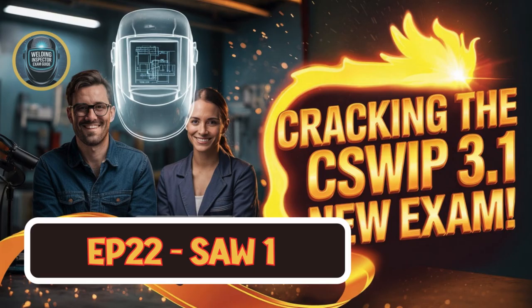Generally, yes, but there's always a limit. If you push the current too high, you risk burning right through the material, especially if it's thinner. Or you can get undercut, little grooves melted into the base plate along the weld edges. It can also create a really deep, narrow bead that might be prone to cracking as it cools. And too low? Too low, and the arc can become unstable, fluttery. You won't get enough penetration, which is often the whole point of using SAW. And you might get lack of fusion. The weld metal just doesn't bond properly to the sides of the joint. You can definitely see distinct profiles if you compare, say, a weld at 350 amps versus one at 650 amps.